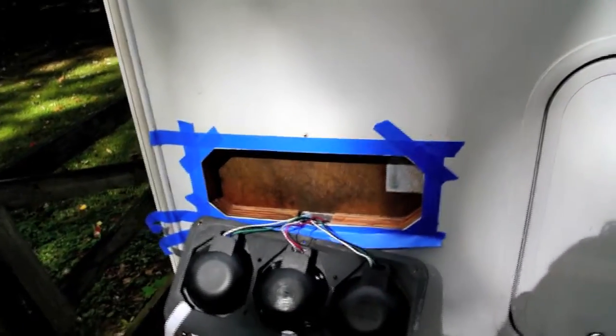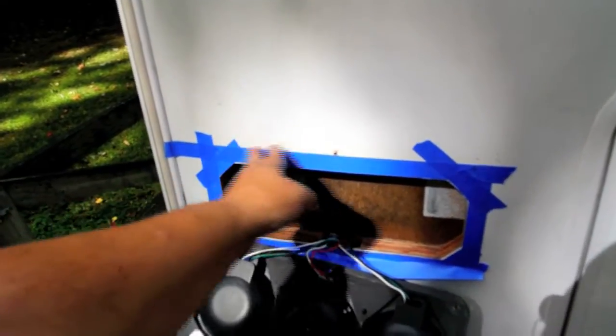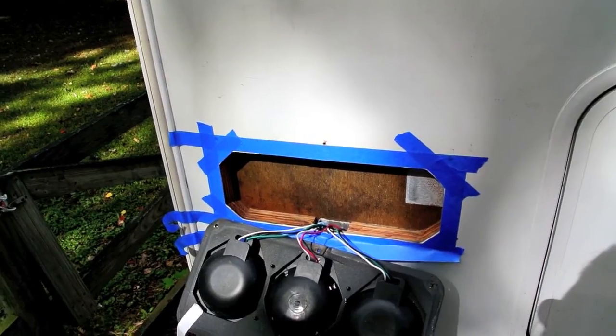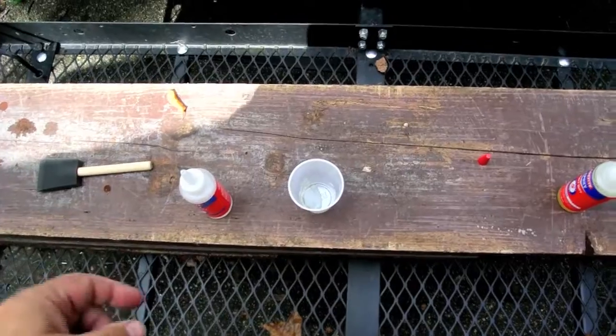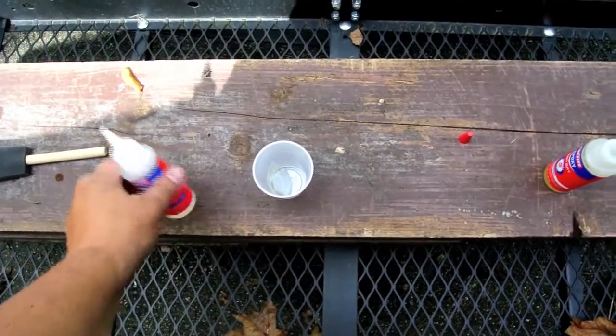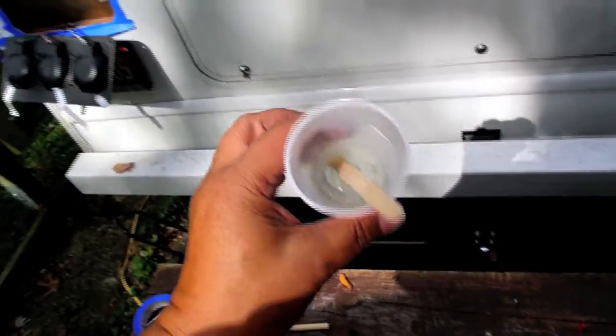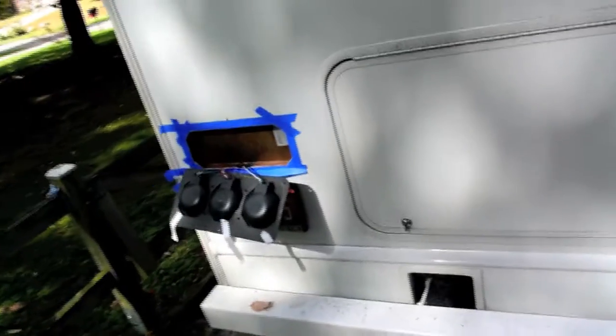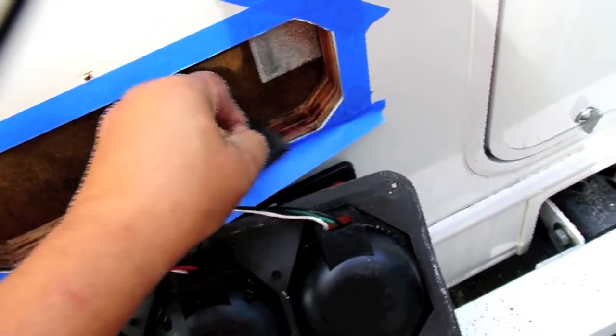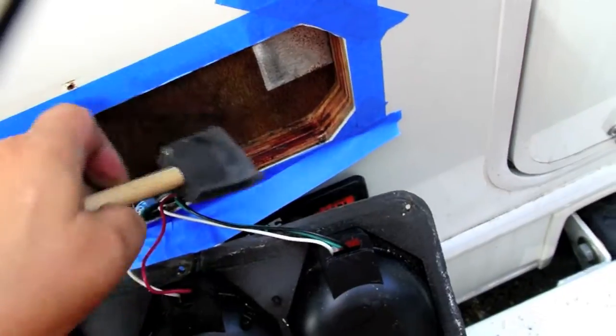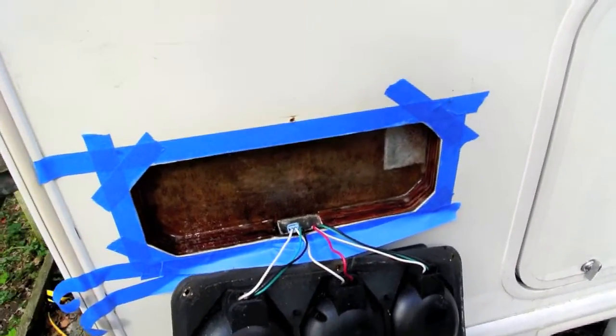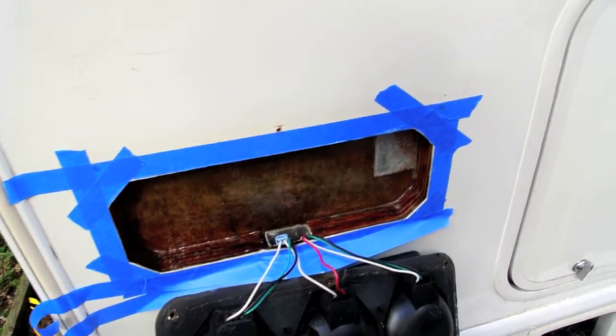Epoxy will stain fiberglass, so take a couple of minutes and put some blue tape around the edges where you're going to apply the fiberglass so you don't get any yellow stains on it. When you mix an epoxy up make sure and keep your caps separated so you don't put the wrong cap on. This particular stuff is 50-50 here. I got some mixed up and we're just going to go over here and slobber it on. To be able to do this you'll probably have to mix the batch up a couple times. This actually does take a little bit of effort to get this wetted out. In some respects it's kind of like trying to paint on molasses.